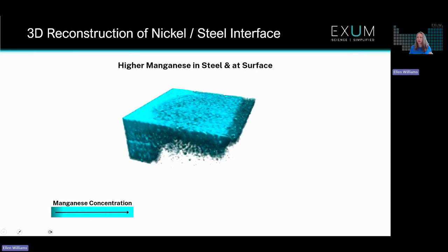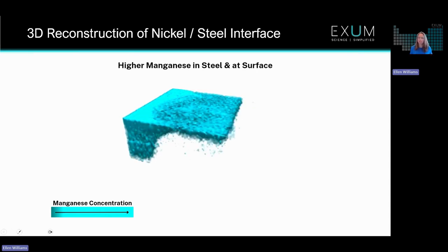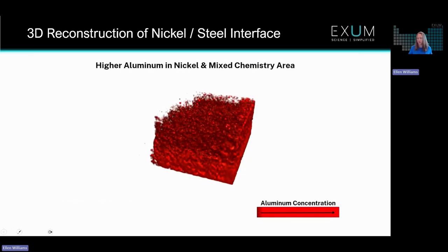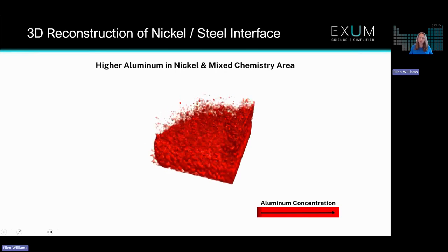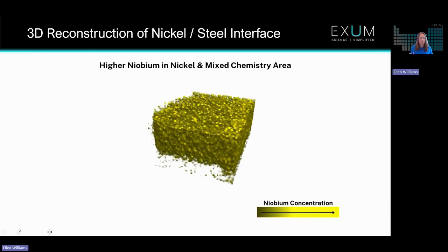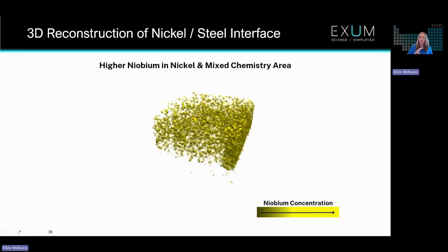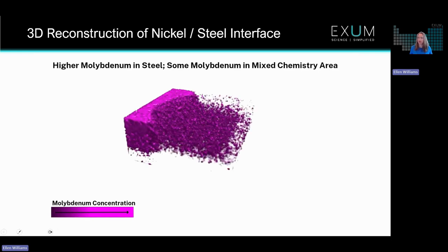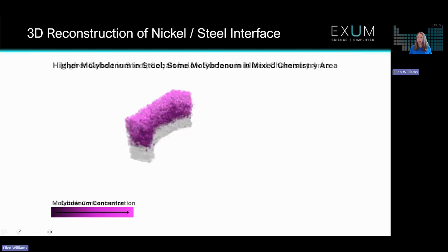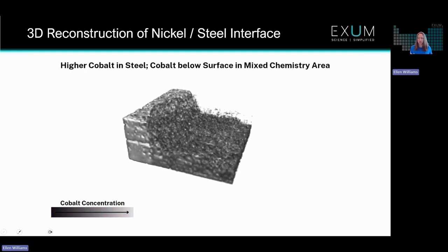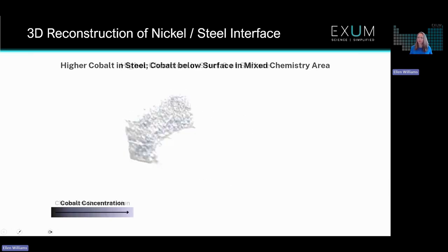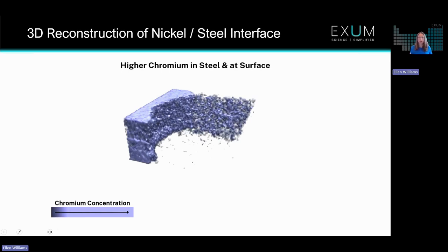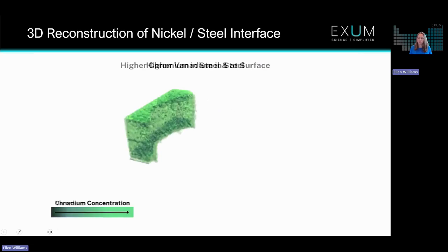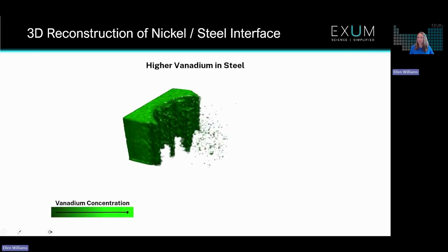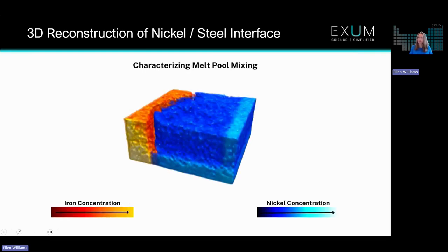So for example, manganese, which is higher in the steel, we see was a big part of the mixed chemistry area. Aluminum was as well. It's primarily concentrated in the nickel, but we do see a decent amount of aluminum in that mixed chemistry in that melt pool bead. Niobium is also a major component of the nickel alloy, but we see it in the mixed chemistry area. Molybdenum, less so. It's more concentrated in the steel. Cobalt was interesting because it was primarily subsurface and wasn't as much on the surface. Chromium showed the opposite trend, where it was more concentrated in the mixed chemistry area on the surface and less so subsurface. And then vanadium was a trace element that was primarily identified in the steel and not as much in the melt pool or the mixed chemistry area. And there's just once again a look at that iron versus nickel, so the steel versus Inconel.